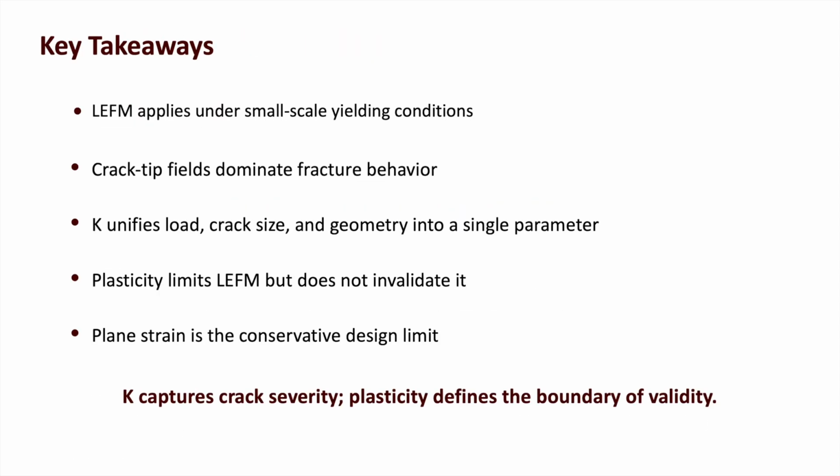Let's summarize the key points from this lecture. First, fracture behavior is governed by the crack tip field, not by the nominal stress alone. Second, the stress intensity factor, K, provides a unified measure that combines load, crack size, and geometry. Third, plasticity does not immediately invalidate LEFM, but it does define the boundary of its applicability. Finally, plane strain typically provides the conservative design condition because plastic deformation is more constrained. The central message is this: K captures crack severity, while plasticity tells us whether LEFM can be trusted.